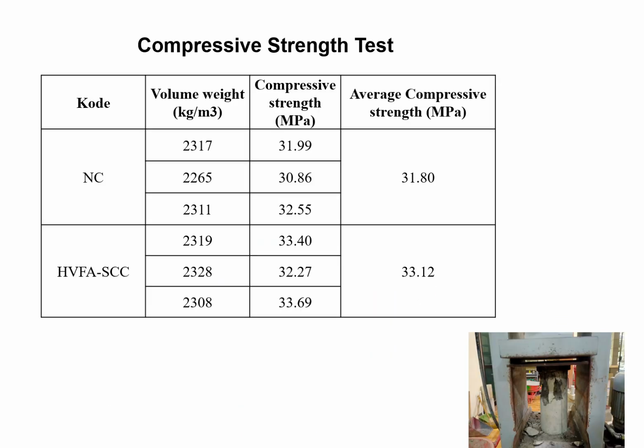Compressive strength test results. For NC the average compressive strength is 31.8 MPa. For HVFA-SCC the average compressive strength is 33.12 MPa. The compressive strength of both types of concrete is nearly the same and meets the requirements for use in structural work according to SNI 2847, 2019.